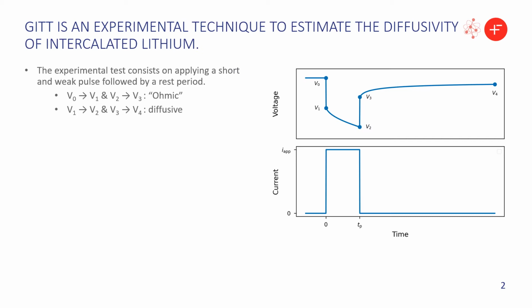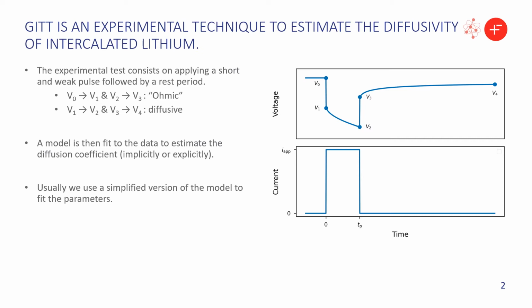And because we are measuring voltage, but we care about diffusivity, what we need to do is fit a model to this data. And that's always the case. In some cases, it's not obvious because we're doing this implicitly, but there is always a model behind that. And with a model, there are some assumptions that we need to be fully aware of. Because what will happen often is that the model we use to run the simulation is not the same we use to fit the parameters. And that's fine, but they need to be consistent. So we need to ensure that the model we use to fit the parameters from experimental data is consistent with the model we're going to run the simulations with, because otherwise the results we're going to get will make no sense.